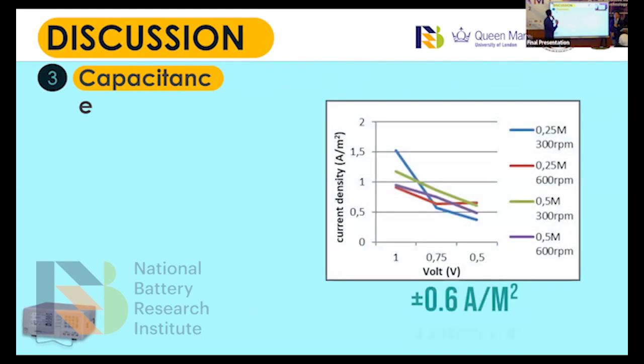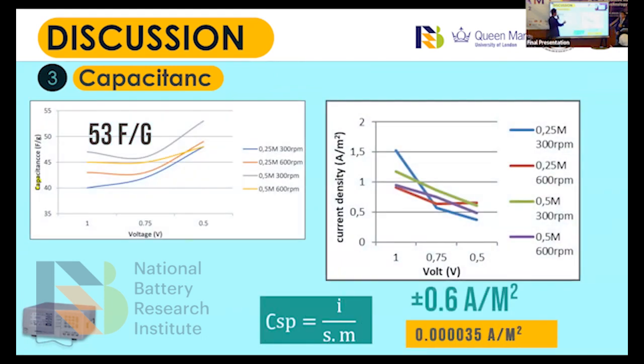And then for the capacitance, as we can see in the data, the manganese dioxide composites have 0.6 ampere per meter squared and the highest value of 53 farad per gram, while the commercial capacitor has only about 0.000035 ampere per meter squared. It's because the manganese dioxide distribution at various concentrations, in 0.5 molar, has the dominant distribution of manganese dioxide, so it can store the charge when doing the storage of supercapacitor and can reduce the size of pores.